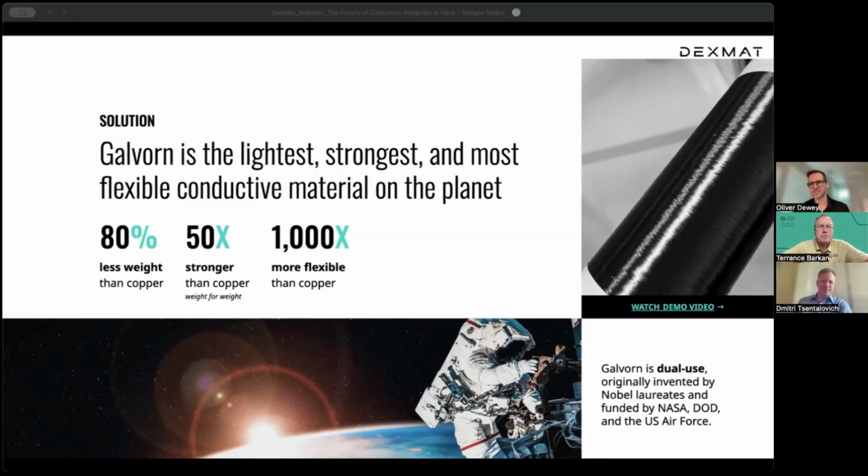Yeah, thanks, Terrence, and thanks to the questioner. It's a great question. When we share out the slides, there's a link to some academic work done at Rice University that I was a part of, where we demonstrate that you can take carbon nanotube fibers produced in that lab and put them back into the solvent, basically neat, redissolve them, and respin them into new carbon nanotube fibers. The key takeaway is that unlike with other polymers, you can mix different grades of carbon nanotube fiber in this recycling process and get new carbon nanotube fiber out.